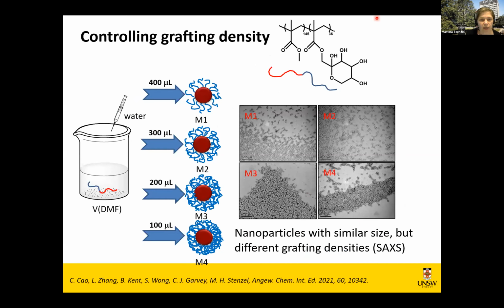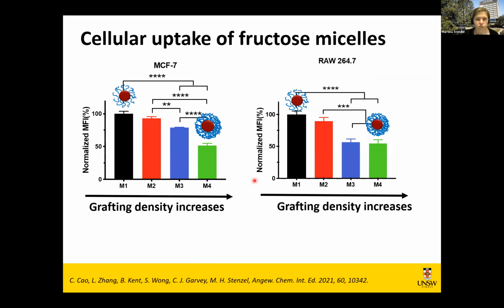So what we are doing here is we are using one block copolymer, and now we process this block copolymer in different ways. And we are getting very different micelle particles with very different grafting densities. If we just look at the transmission electron microscopy picture, they all look the same. These particles are all around 30 nanometer in size. However, again, from SAXS measurements, we know that they have indeed very different grafting densities.